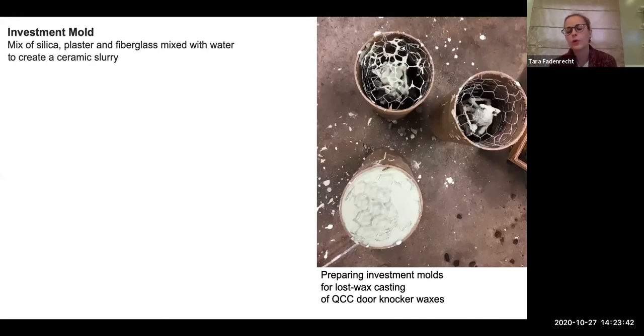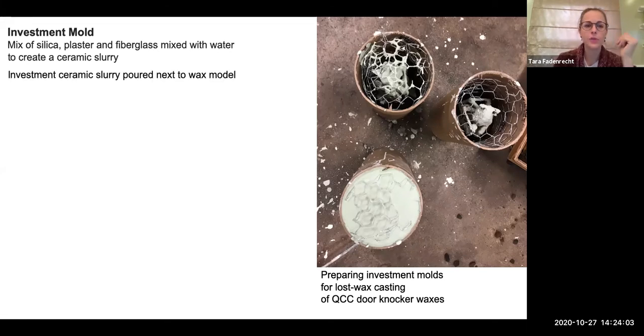So once you have your waxes sprued and gated, this is a vertical overshot. You need some sort of mold container that your ceramic slurry can be poured into. What you'll see here is that on the top of some of these, they have a skim coating of the ceramic slurry. This helps pick up all of those details, all the hair, the small parts of the nose, what have you. This type of investment mold, the fidelity is so extremely high that not only will it pick up all those little details, it will also pick up your fingerprint if that exists on the wax.